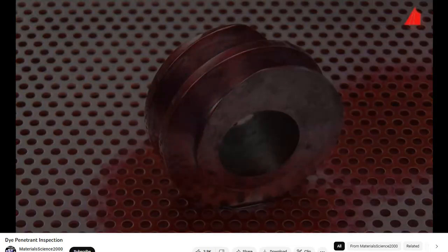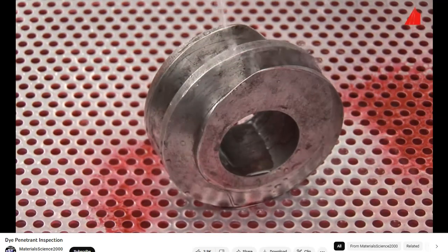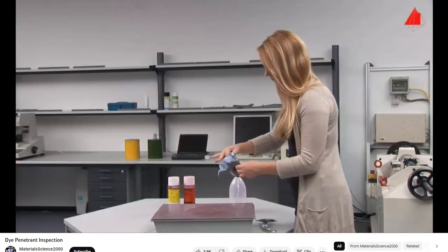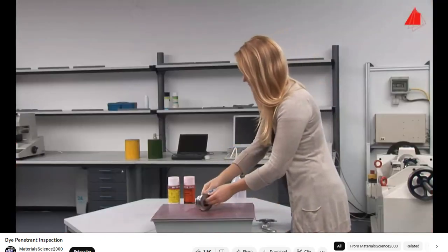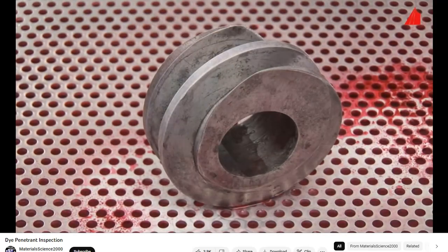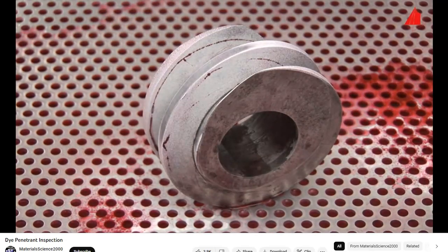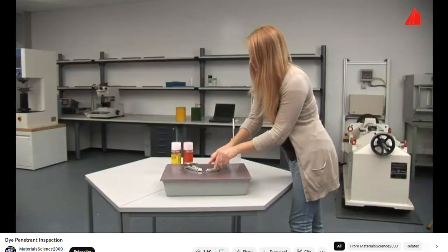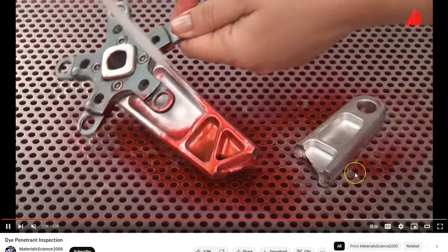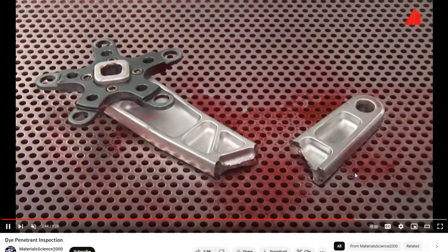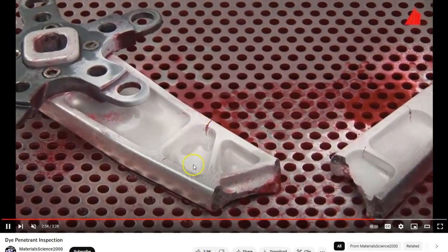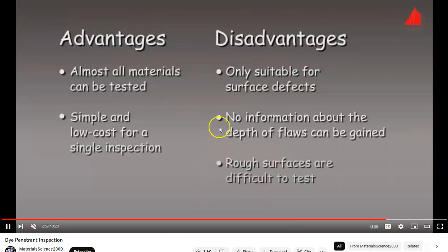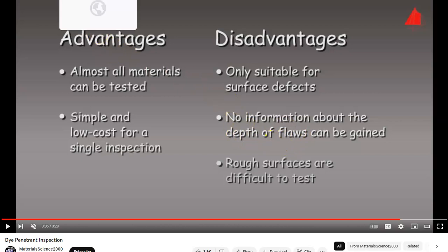We wash it off. We then spray on a developer, that foam, and the crack will then spread out. It will be absorbed into the foam and we'll be able to see it. So here we have an object. It's got the dye washing the penetrant away. You've got to give it 10 minutes to actually set in and then spraying the developer, the foam. And then we can see that crack just form.